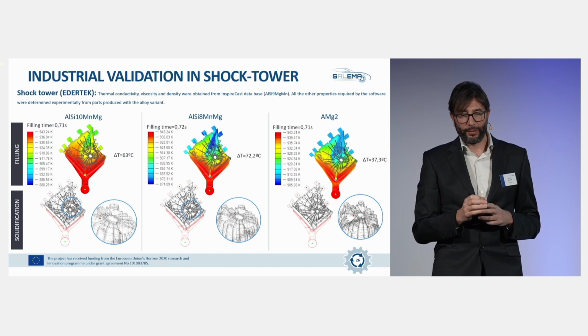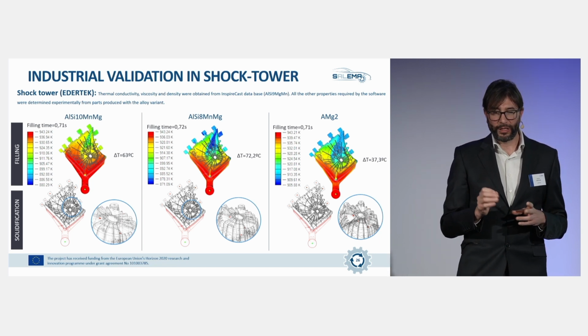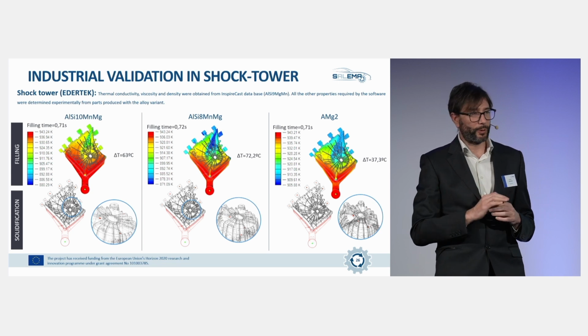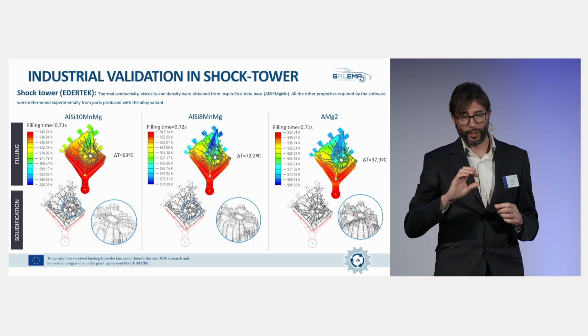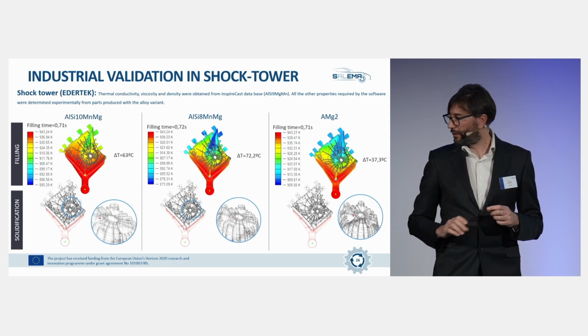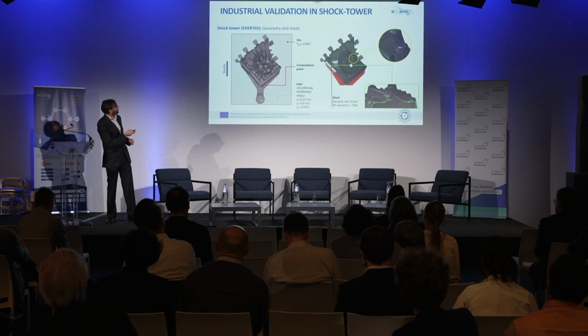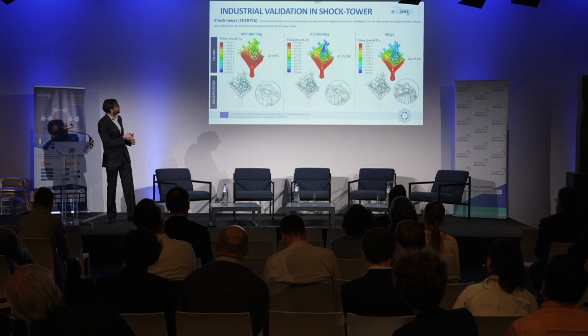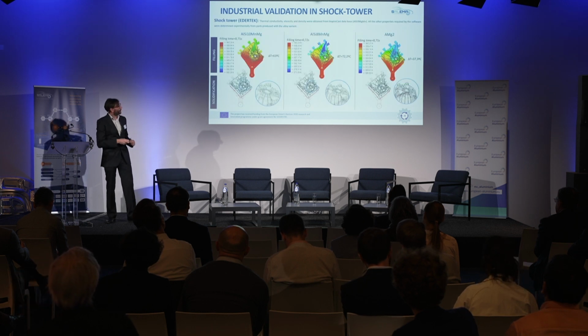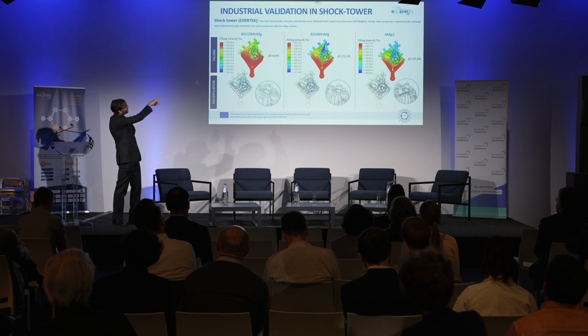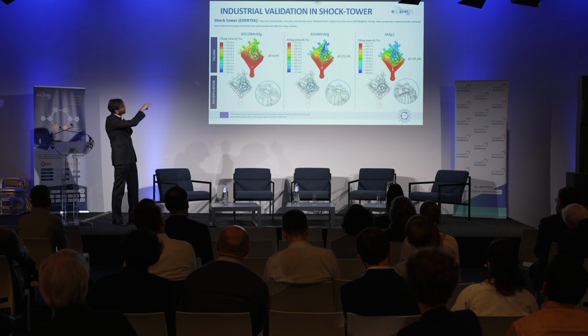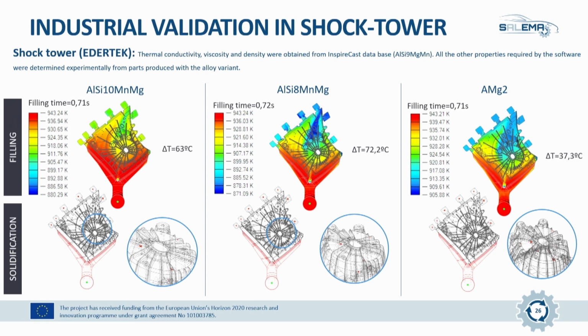For the aluminum, silicon, 8 manganese, magnesium, and especially the aluminum, magnesium 2, it was different. We observed that there was higher cooling, and it could be a freezing region just here. So you saw on the top this dark blue, that it's colder, that it can represent a problem. So we needed to increase melt temperature and or the injection speed in order to get a good quality component.